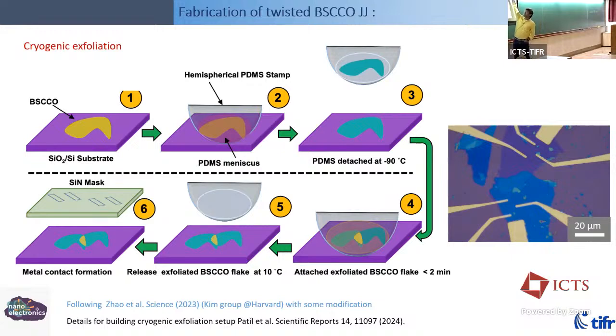You know, these set of electrodes here, you send the same current through, which goes through the Josephson junction and the two flakes, and you check the health of these two guys. These electrodes tell you about this, but if you measure this guy and the other one, then it tells you expressly about the Josephson junction. It will have BSCCO. Yeah, it has some BSCCO for sure, but as I told you, the critical current of the BSCCO which is flowing in plane is much larger than that of the Josephson junction, which is the weakest link. So any feature that shows up as you switch it will be from that Josephson junction.